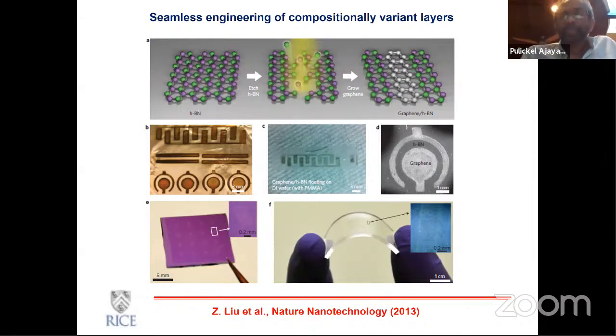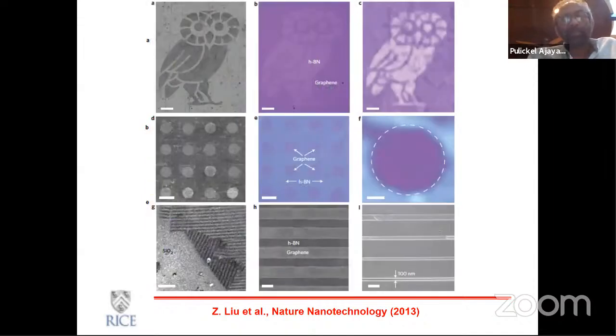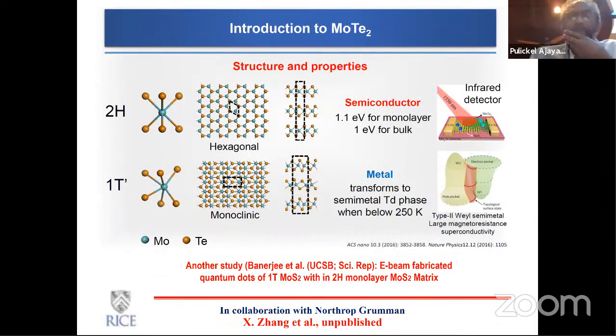And one can think of structures like this as, for example, an antenna, all 2D antenna structures. It's metallic and insulating matrix. So there's all kinds of engineering that you can do at the nanoscale within these two-dimensional layers. And that's been really very, very interesting. And some patterns that you're seeing where we have managed to create different types of in-plane architectures of boron nitride and graphene. There is another system that we have also been playing around with, very similar to the boron nitride and graphene for the in-plane heterostructure.